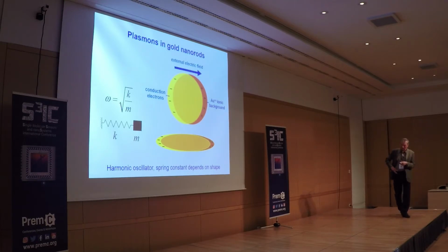And when you excite these particles optically, you apply a variable electric field, an AC electric field that moves the electrons back and forth with respect to the heavy ions. And this translates into a very large dipole moment, which will interact very strongly with the light. And this will give rise to scattering, but also give rise to a large surface density of charges.